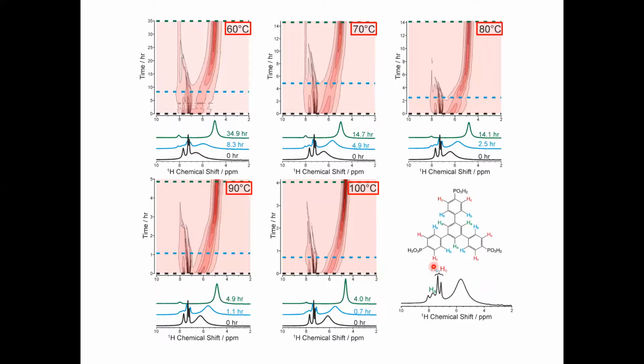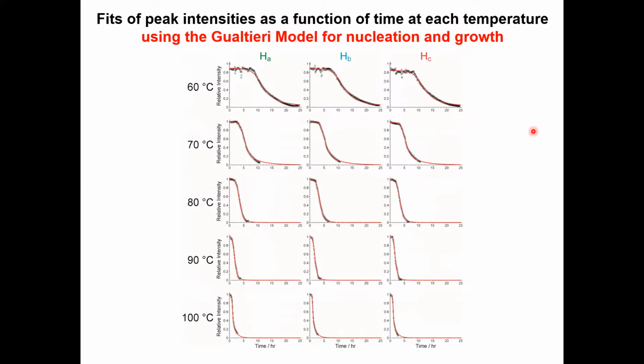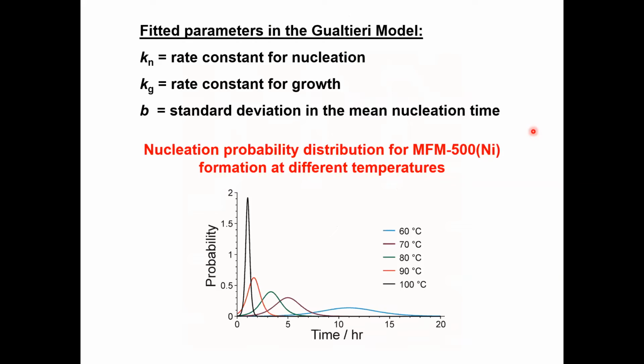So here we see at different temperatures, as indicated, the evolution of the liquid state proton NMR spectrum. And we're going to be focusing in particular on the three different proton environments in the linker, as shown here, and how they evolve as a function of time. And integrating the signals for these different proton environments, and then looking at how these intensities vary as a function of time, these have then been fitted using what's called the Gualtieri model, a very commonly used model to describe kinetics of the formation of microporous materials, MOFs, and so on. And we see very, very good fits to the data as shown here. We can extract from those fits information such as the rate constant for nucleation, the rate constant for growth, and another parameter which gives the standard deviation in the mean nucleation time.